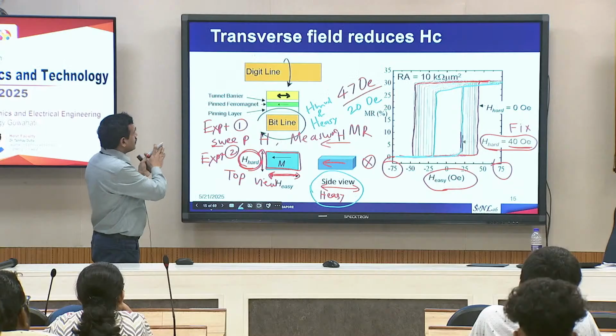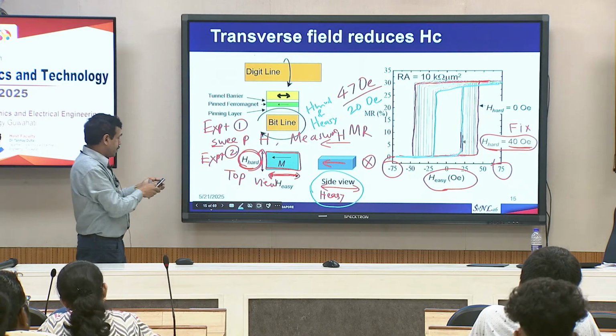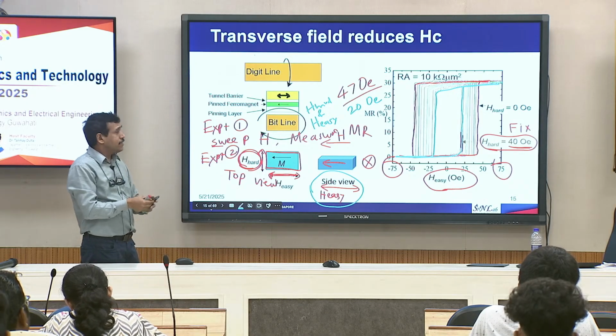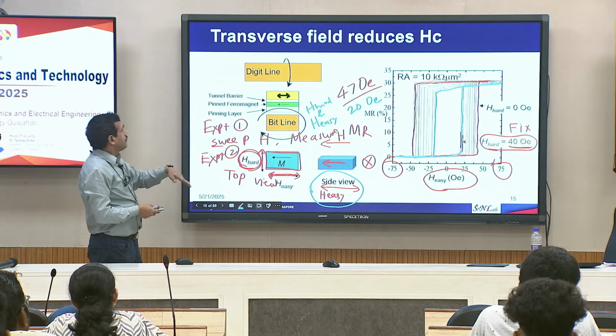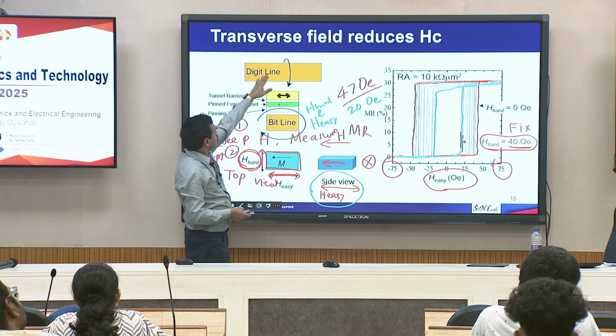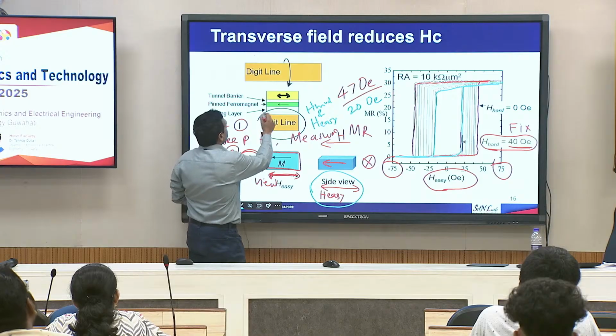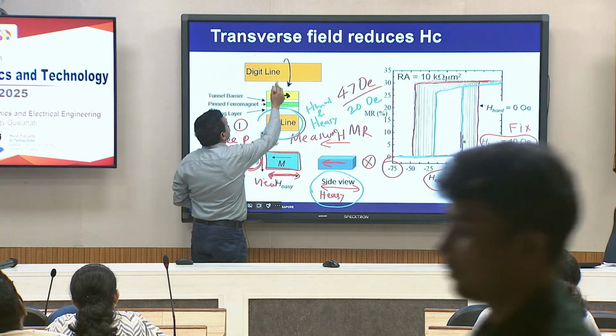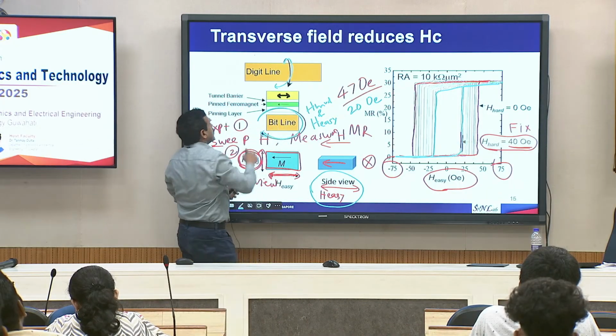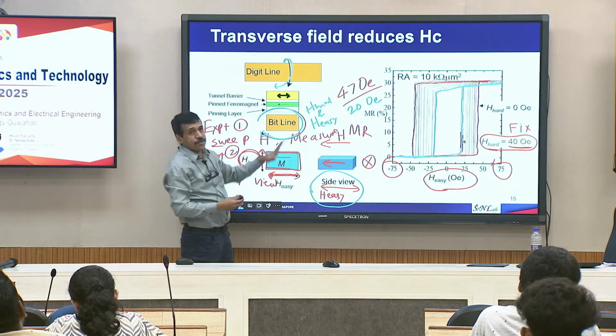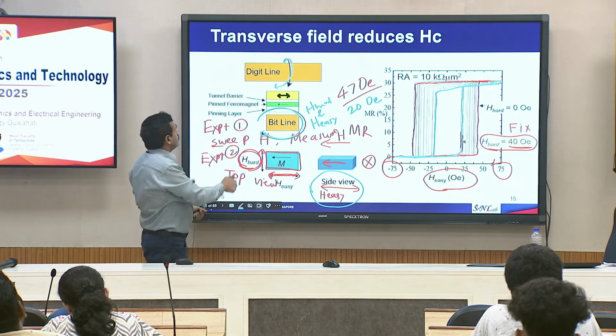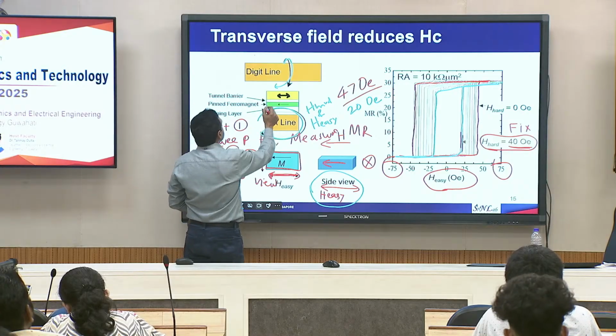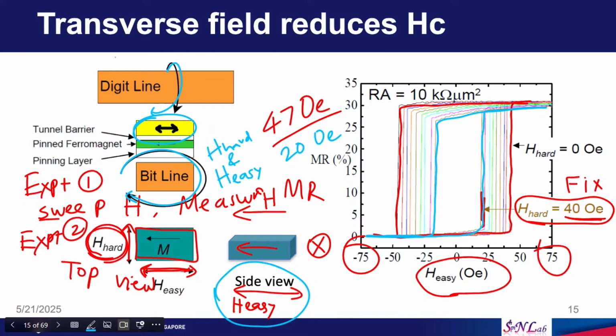So, this is what we do in selective switching. We are applying two orthogonal fields. If you remember, we have a bit line and a digit line, both of them generating a magnetic field. We are using two magnetic fields orthogonal to each other, which means the coercivity of the free layer here will be much lower than the coercivity of all the other MRAM cells.